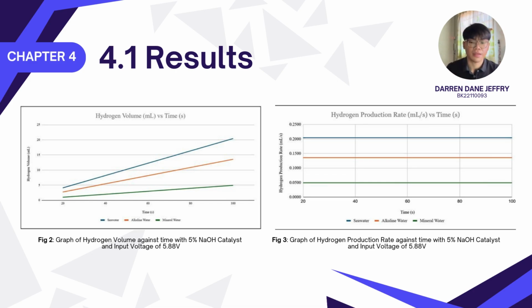pre-treatment per se. For alkaline water, a consistent rate of 0.135 milliliters per second was observed, making it suitable for controlled environments. While its rate is lower than seawater, the lack of significant byproducts makes it a dependable choice for industrial setups. Mineral drinking water, however, with a rate of just 0.048 milliliters per second, has the slowest rate of all the 3 electrolytes. It was inefficient and also energy intensive. The high energy demands reflect the inability to compete with the other 2 electrolytes in terms of scalability and cost effectiveness.